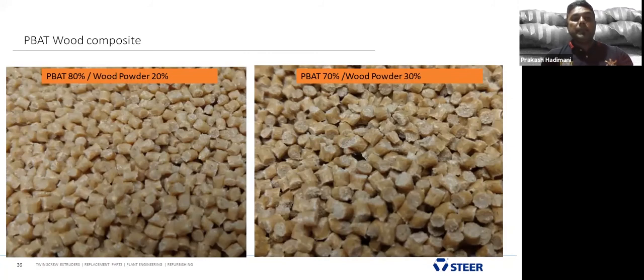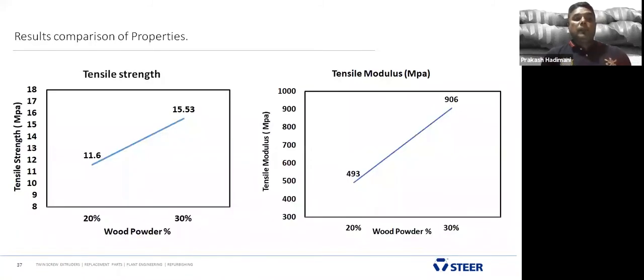What we did was 80% PBAT, polybutylene adipate terephthalate, and 20% wood composite. We blended and observed good dispersion, and we also added 30%, and we are thinking of going to 40 and 50. That is the next study we are planning, still going for 40% of wood composite in the PBAT. We tested in the UTM. These are the mechanical properties we studied.